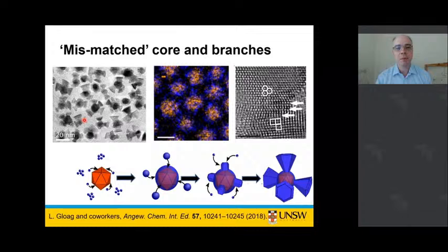So if we have a look at the particles we make, rather than growing off very precise crystallographic faces, we actually grow off in very random orientations. And if we have a look at how the growth occurs, then first of all, we get a ruthenium shell growing on our gold core.